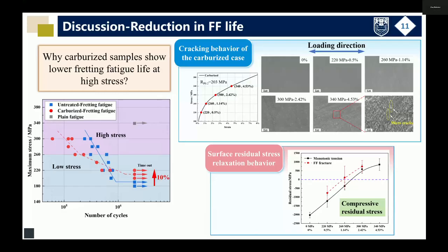To further understand why carburized samples show lower fretting fatigue life at high stress, we examined the surface features of carburized samples after different cycle levels and measured their residual stresses. The result shows that at high stress, initial cracks form directly in the surface of the carburized case, which means that damage is already introduced during the first cycle of fretting fatigue. On the other hand, residual stress measurements also indicated that although the compressive residual stress is not completely relaxed after the first cycle, the residual stress in the fractured sample turns into tensile stress, which is harmful to fretting fatigue.